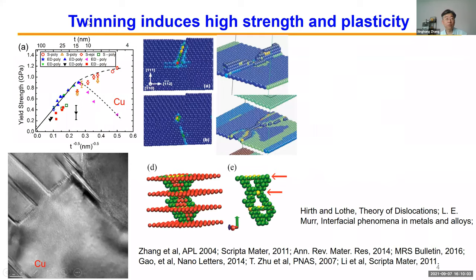So I begin by showing this. What you see here is that nanotwin metal has been studied for well over a decade. It has been known in the community that nanotwin metals can have high strengths. For example, if we look at this chart comparing the yield strength versus 1/√t, where t is twin thickness, for copper, smaller twin thickness is stronger. So nanotwins can introduce high strengths.